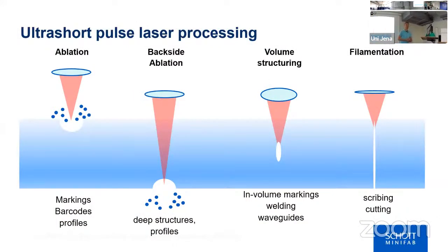So for ultra-short laser pulse processing of glass, you have basically a few processes. At first, you have the standard ablation on the surface, which you also have with metals. Glass is transparent. You can also focus your laser beam on the backside, so you can make a backside ablation. You can focus it in the volume, like we have seen for the fibers, for example. And we have this last process, filamentation, which is a mix of all this. You focus in the volume, but your modification typically extends from bottom to surface in a tiny area.